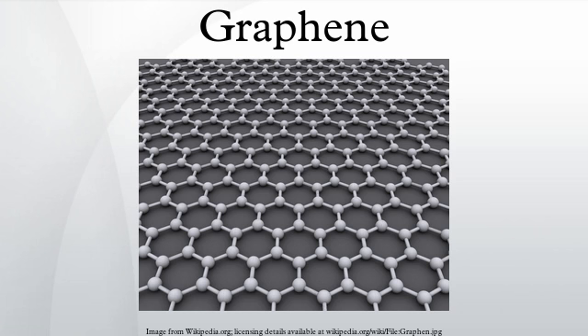Nonlinear Kerr effect. Under more intensive laser illumination, graphene could also possess a nonlinear phase shift due to the optical nonlinear Kerr effect. Based on a typical open and close aperture Z-scan measurement, graphene possesses a giant nonlinear Kerr coefficient of 10^-7 cm²/W, almost 9 orders of magnitude larger than that of bulk dielectrics. This suggests that graphene may be a nonlinear Kerr medium, paving the way for graphene-based nonlinear Kerr photonics such as a soliton.